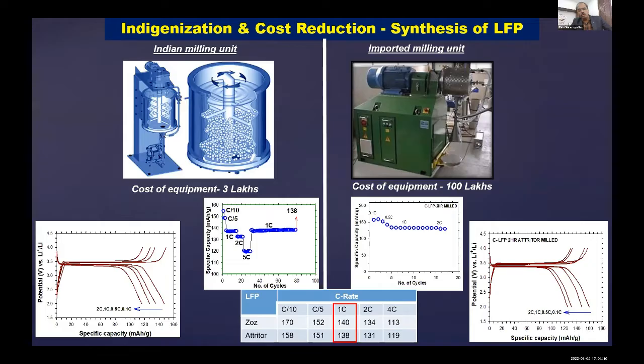So how to do that? It is very easy to make lithium iron phosphate. Anyone, even a high school kid, if he knows a little bit of chemistry, can take the raw materials, mix them, and then do the solid state synthesis. But LFP, lithium iron phosphate, is an insulator by itself, so it cannot draw the current. So LFP has to be coated with carbon. And that's the first thing.